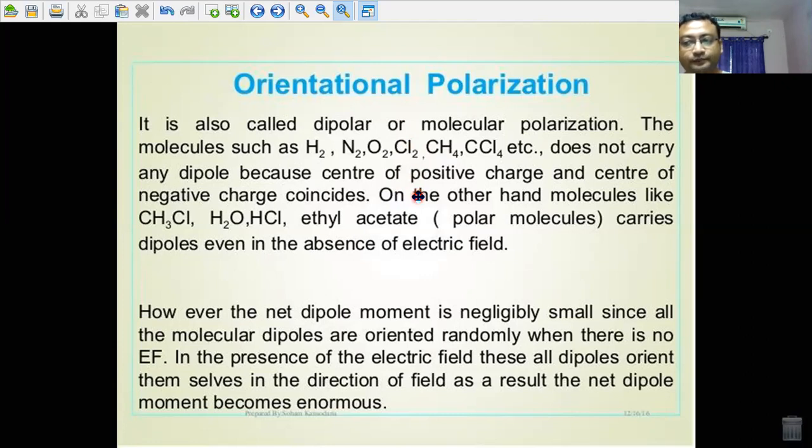So, these dipoles are not free to rotate in the solid, which they do in the liquid or gas phase. An applied electric field helps orient these dipoles along the direction of the field. Such an orientation is opposed by the thermal agitation, which tends to randomize the dipoles. It is because of this reason that the calculation of dipolar polarizability has to be made under thermal equilibrium.